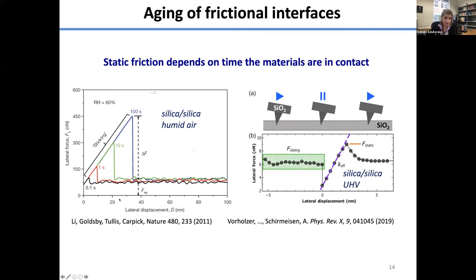On the left-hand side are experiments, again from Rob Carpick's group, in humid environments on silica. And it's showing that static friction, or friction here, lateral force, as a function of displacement, increases with the contact time. The different colors represent how long the tip was held in contact prior to sliding, so this is 100 seconds. And on the right-hand side, this is a similar experiment that had been reported by Anders Schirmeisen in ultra-high vacuum on silica as well. So both of these are single asperity AFM experiments.